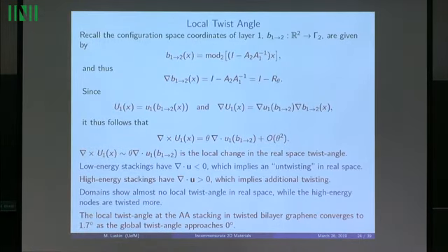Okay, now another interesting thing. We have two ways of looking at our problem: real space and configuration space, and here's the mapping. If you just do your calculation, take the gradient of this mapping with respect to x, you'll see that the curl of the real space displacement is equal to theta times the divergence of the configuration space displacement.